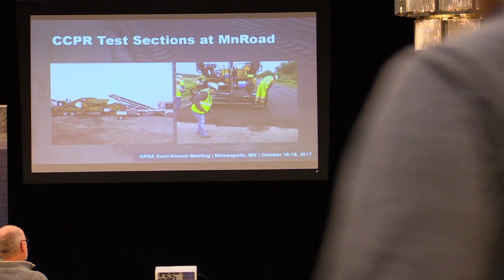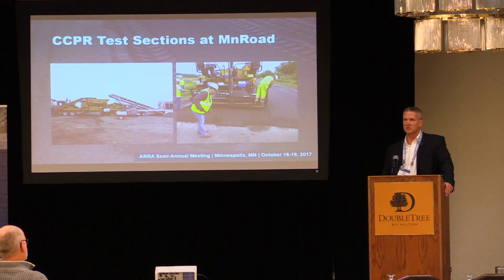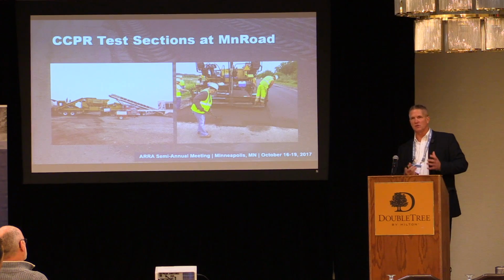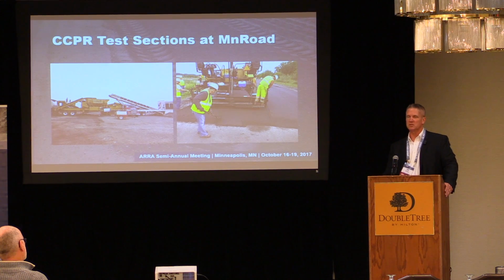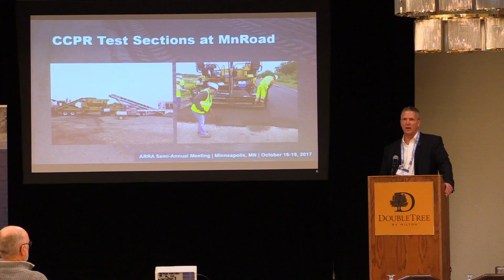I'm really happy to see some foamed asphalt get out on that roadway. One thing that I did notice that I haven't seen with foamed asphalt in the past is that very good coating on the coarse aggregate particles in the foamed asphalt section when I was out there. Normally you see foamed asphalt really coats the fine aggregate, which holds those coarse aggregate pieces in place. But talking to other people in the industry, I've found that certain binders, certain asphalt cements, as related to the half-life and the expansion ratio in combination, will provide better coating in the foamed asphalt environment. And I think the asphalt that was supplied here is certainly one of those, because excellent coating, probably the best I've ever seen on that material.